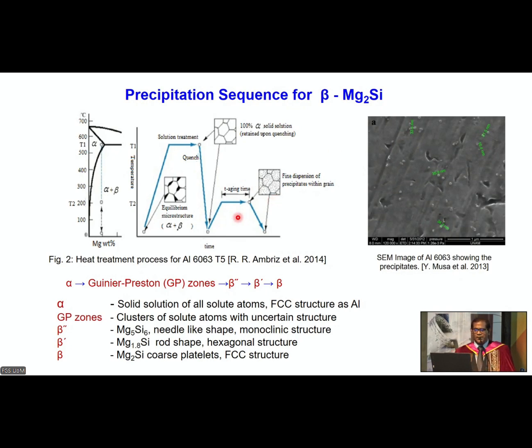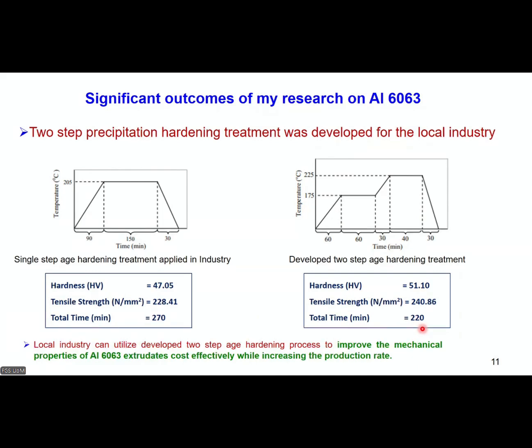Yes, so this is the aging treatment I discussed. I am talking about that treatment. Here, as you can see, the hardness and strength gained for the extrusion is nearly 230 megapascal. And the total time period for this heat treatment is 270 minutes. With the development of the two-step age hardening process, the total time period is reduced to 220 minutes. That is the significant finding in this research: a 50 minute reduction in the aging time period.